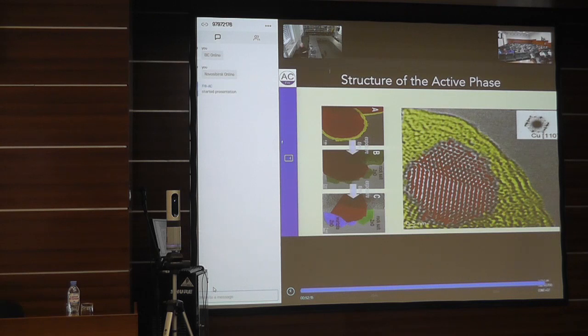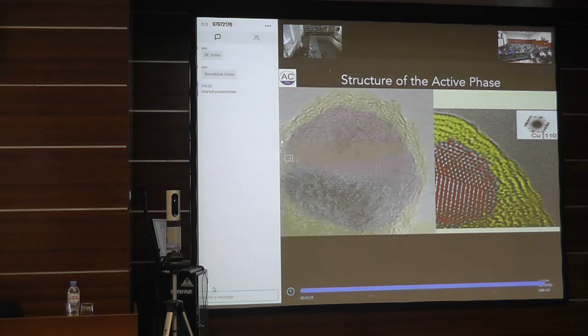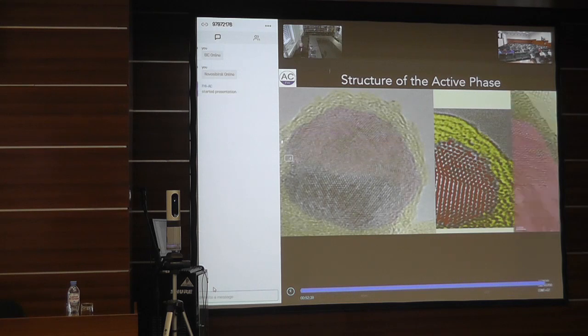So very low dose conditions, and you can see this. Now when you look at the second piece of information why this could be dynamic, it comes from the deactivation studies. We now do an identical location TEM experiment of one copper particle that we study fresh, and then we study the very same particle after half a year of operation under 50 bar pressure.